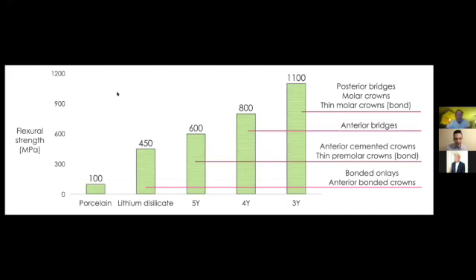But these are just my thoughts on the strength and how that means the materials could be used clinically. So like porcelain, of course, porcelain has no crystals in it. It's got a few crystals in it, but it's mostly glass material. It's only strong enough to exist in the mouth if it's bonded to enamel or bonded to the coping of a PFM or PFZ. And it's got a strength of about 100 megapascals. Lithium disilicate is in that 450 range.